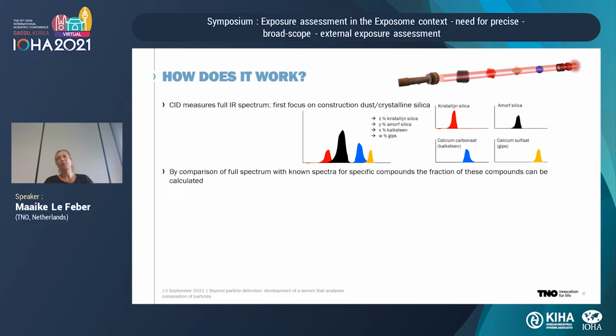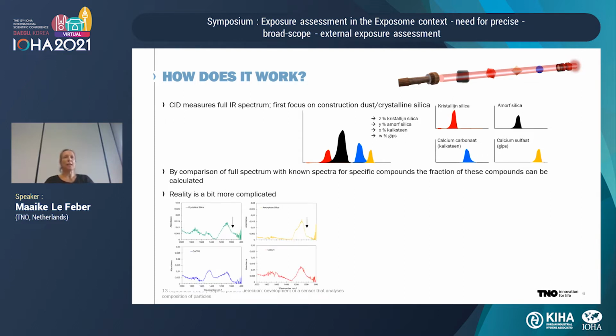Each of them is characterized by a specific absorption peak at a specific wavelength. So if we have the combination of all particles in the hollow waveguide, we get a spectrum with four typical peaks. So the wavelength of each of the peaks identifies the compound, while the height of the peak in relation to the other heights can be used to calculate the fraction of each of the substances in the mixture. Of course, this is a very simplified example. In reality, it is a bit more complicated.